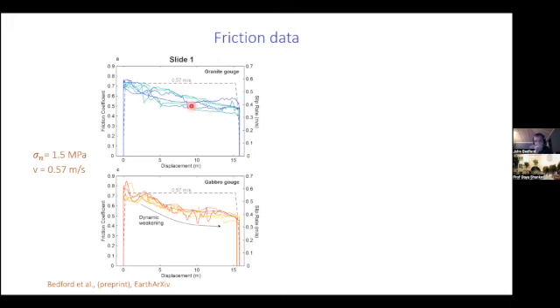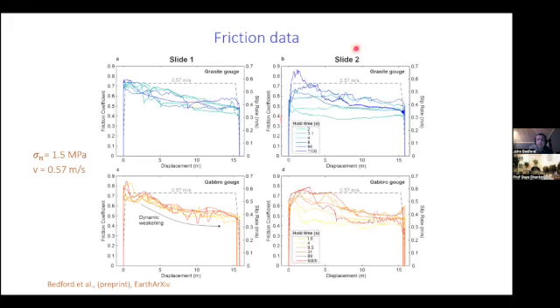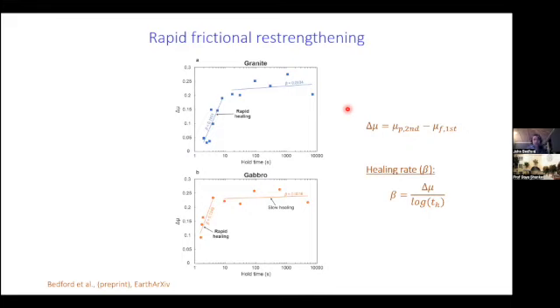We held them all for different amounts of time, and we found that in the second sliding event, the peak friction that was achieved is dependent on the hold time during the hold period, with layers that were subjected to long hold times achieving a higher peak friction, which is exactly what you see in low velocity slide-hold-slide experiments. But what we want to do is compare the healing rate, and to calculate the healing rate, what we do is we take the peak friction from the second sliding event, and we subtract the final friction from the first sliding event.